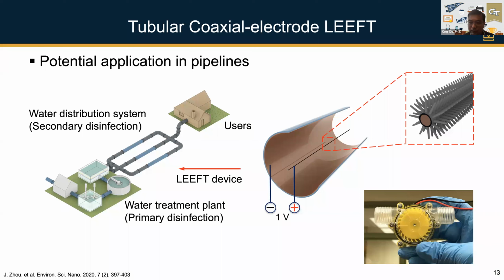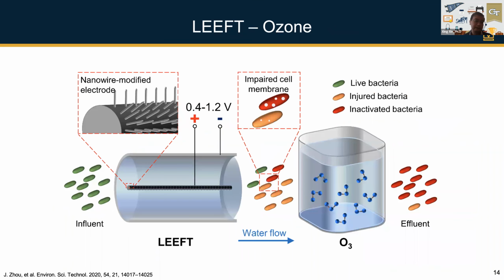Okay, so back to what I just mentioned: LEEFT itself is probably still not very acceptable at this point. It's still a long way to go, but I think LEEFT can already be a good pretreatment technology, or can be combined with some existing technologies to achieve synergistic disinfection. What we have demonstrated here, for example, is that we can combine LEEFT with ozone. The idea is that you use LEEFT to treat the bacteria first, not necessarily to the point that they all get inactivated, but some of them get killed, and a lot of them already get hurt, and then you do the ozonation after that.